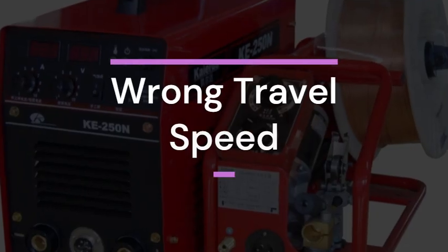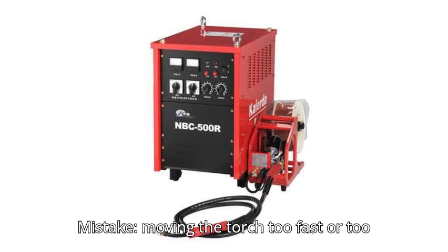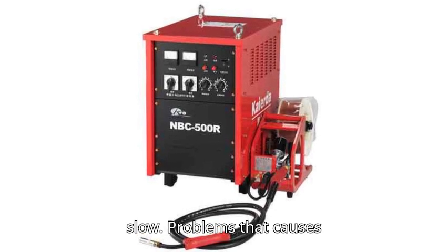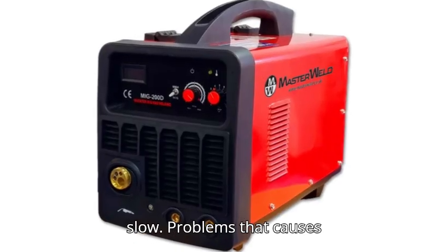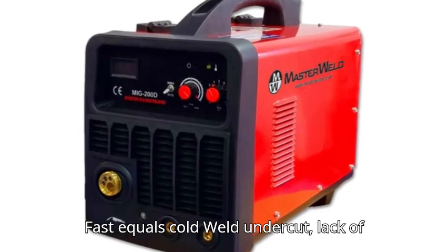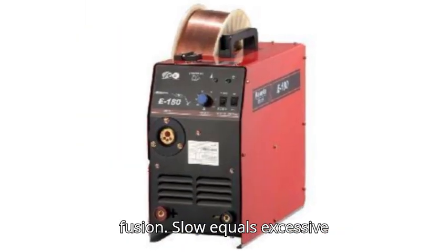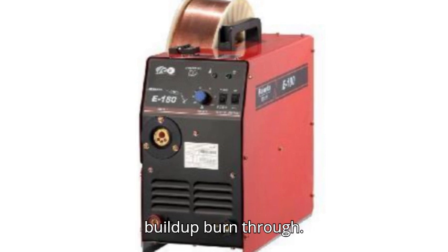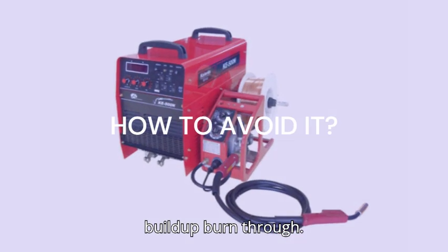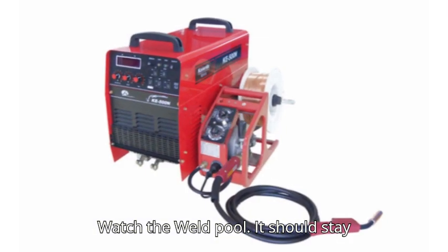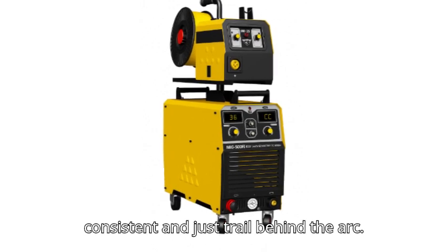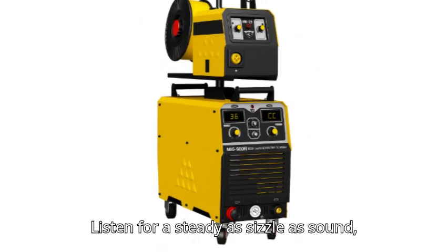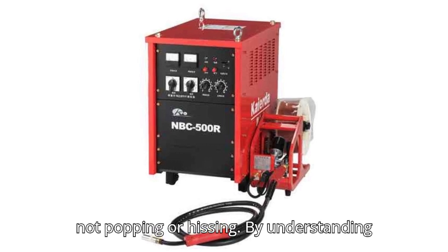5. Wrong travel speed. Mistake: moving the torch too fast or too slow. Problems it causes: fast equals cold weld, undercut, lack of fusion. Slow equals excessive buildup, burn through. How to avoid it: watch the weld pool; it should stay consistent and just trail behind the arc. Listen for a steady sizzle sound, not popping or hissing.